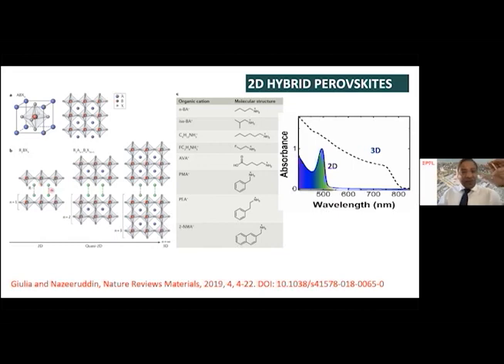What it gives you is that n equals 1 is a highly blue absorbing material. As we increase the n number, it goes to a normal three-dimensional perovskite. Here on the middle C panel, I have highlighted a couple of cations, but there are plenty of cations. The main cation which we'll be discussing is phenyl ethyl ammonium, followed by substituting protons with fluorine groups.